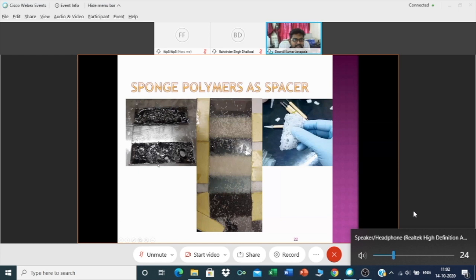As you can see, the attempt failed completely; some bubbles are bigger, some are smaller. Then I came across one fantastic paper. They are using sugar cubes to make the polymer substrate. So I made it with pure PDMS, TiO2, and GO embedded. The TiO2 one got dispersed while cleaning and it failed. You can see some of the polymer broke and dissolved when I was cleaning.